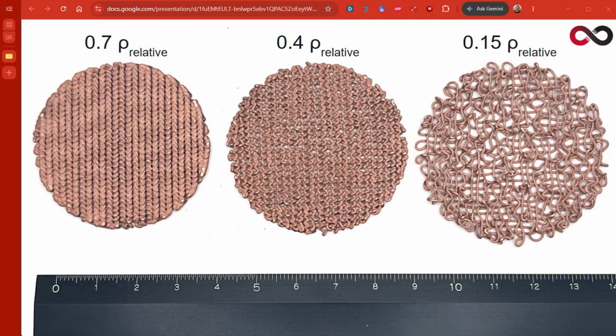And while the three here are all homogeneous, we maintain the ability to mix these together and with any density in between arbitrarily. So for example, Miski was just showing something that looks like a solid exterior with a porous interior. We're able to tune the actual density itself. That was intended to be a rudimentary heat pipe. So you can flow a thermal liquid through the center, and it would be able to mix with a high surface area with the actual heat pipe itself.